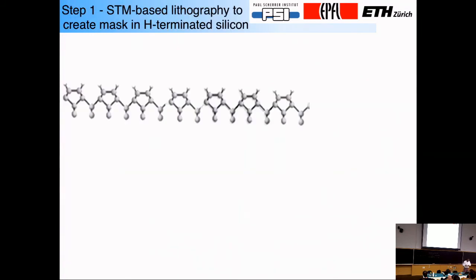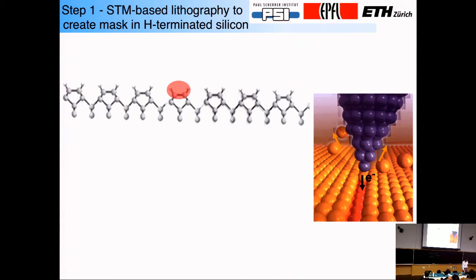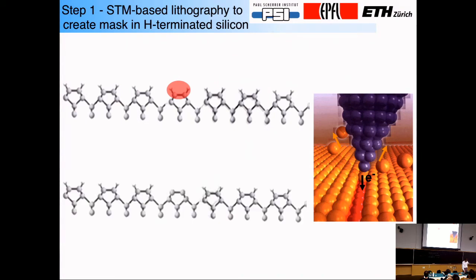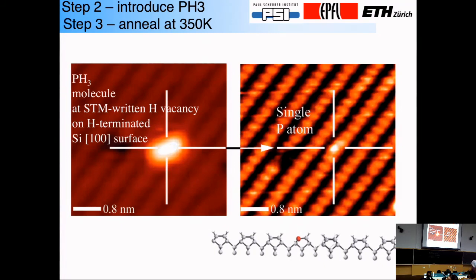So I've shown you how you work with lithography. I've shown you how you create, essentially deterministically, these dangling bonds and dangling bond patterns on top of silicon 100. The next step is what will lead to implementing what I just asked. In particular, you could introduce phosphine into the vacuum chamber. The phosphine looks for unhappy electrons, and these are the dangling bond states. So what happens is a phosphorus goes to these places where we have missing hydrogen atoms.